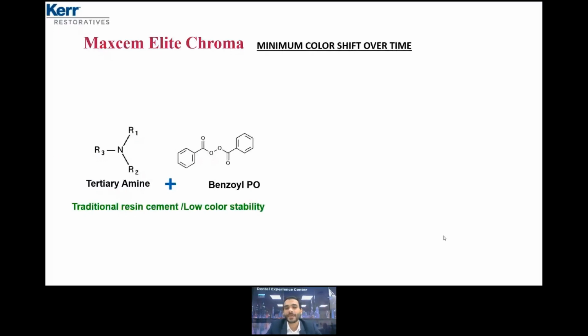High color stability. Maxcem Elite Chroma is a dual cure cement, and as we know, dual cure means light cure and chemical cure, so you have both options. In order to have a chemical cure, we need to add a catalyst, initiators, to start the polymerization process. 95% of dual cure cements use specific initiators. I don't like to go into chemistry, but let me mention this point. They use tertiary amine and benzoyl peroxide.